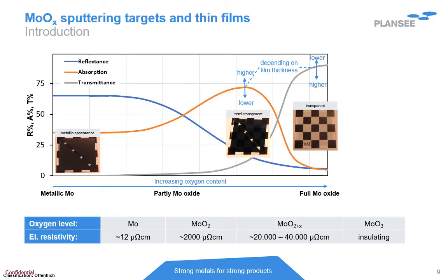Another group of materials I want to cover in my talk today are molybdenum oxides. Molybdenum oxides are a very special group of materials with a broad range of different properties depending on the oxygen content. On this graph here, you see some general information on optical properties as well as on the electrical resistivity. For pure molybdenum on the left side, for example, the optical reflectivity is the highest and the electrical resistivity is very low due to the metallic character of this material.